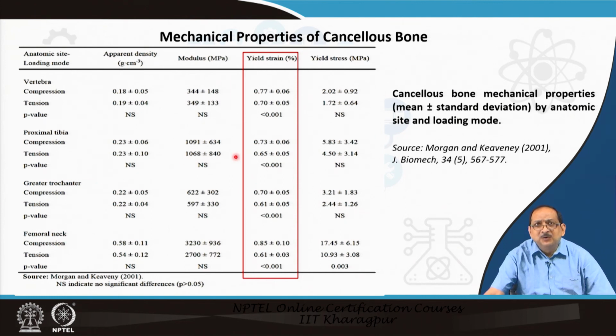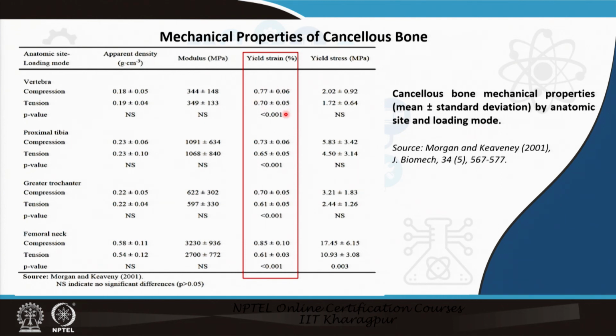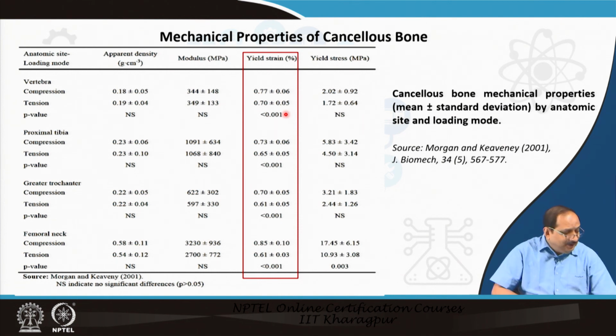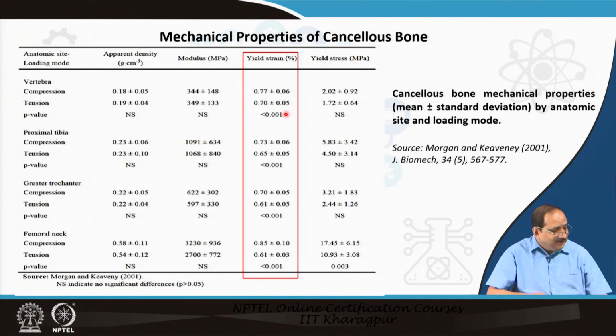If we have a closer look, we see that there is variation of the yield strain from one anatomic site to the other, but within a single anatomic site, the variation in the yield strain behavior is very small, which means that the yield strain is more or less uniform within the site, providing a strong argument for the utility of a strain based description for describing failure of trabecular bone.